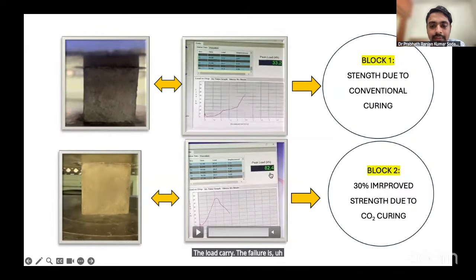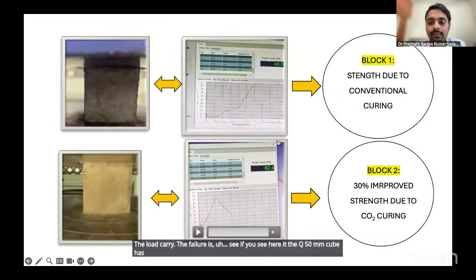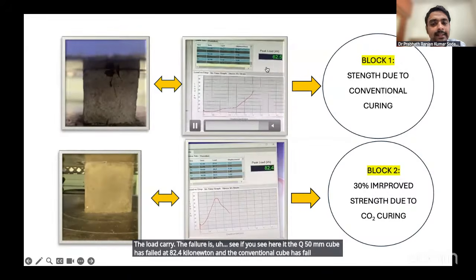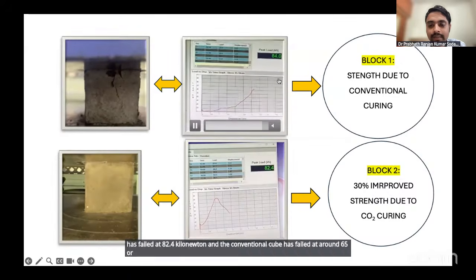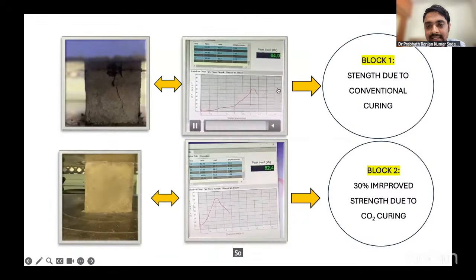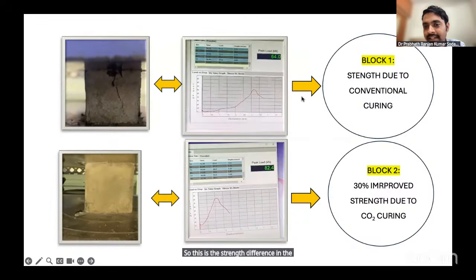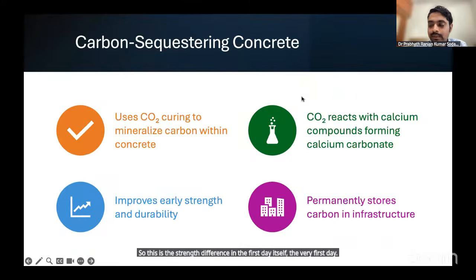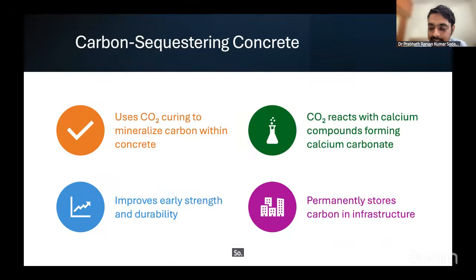The failure is, if you see here, the 50 mm cube has failed at 82.4 kilonewton, and the conventional cube has failed at around 65 or 70. It will be close to that. So this is the strength difference on the first day itself, the very first day. So carbon sequestration can be done in the initial days only.